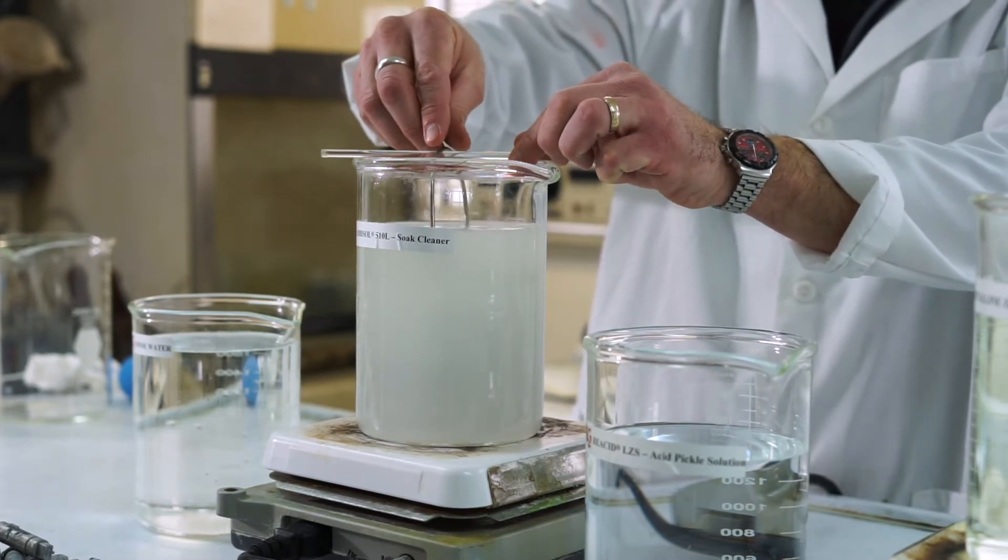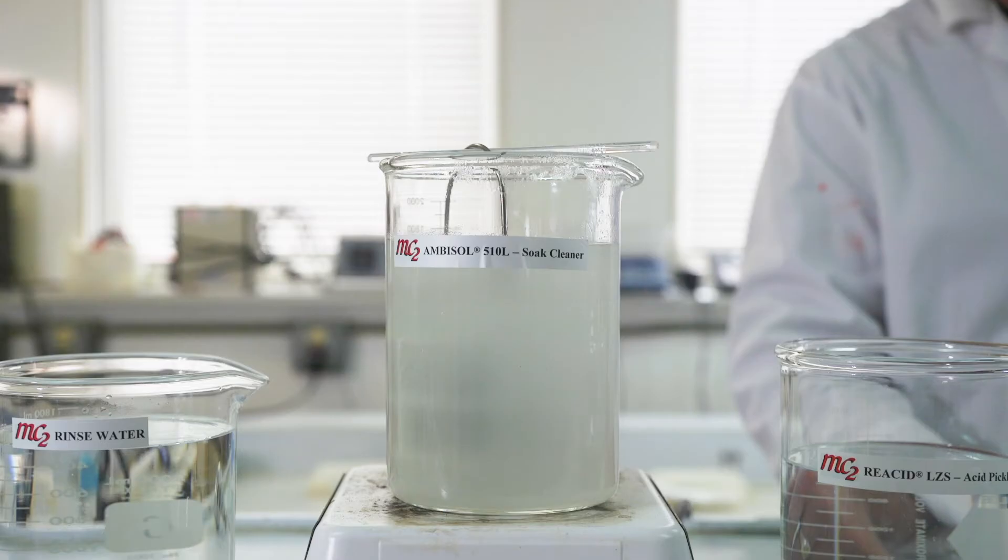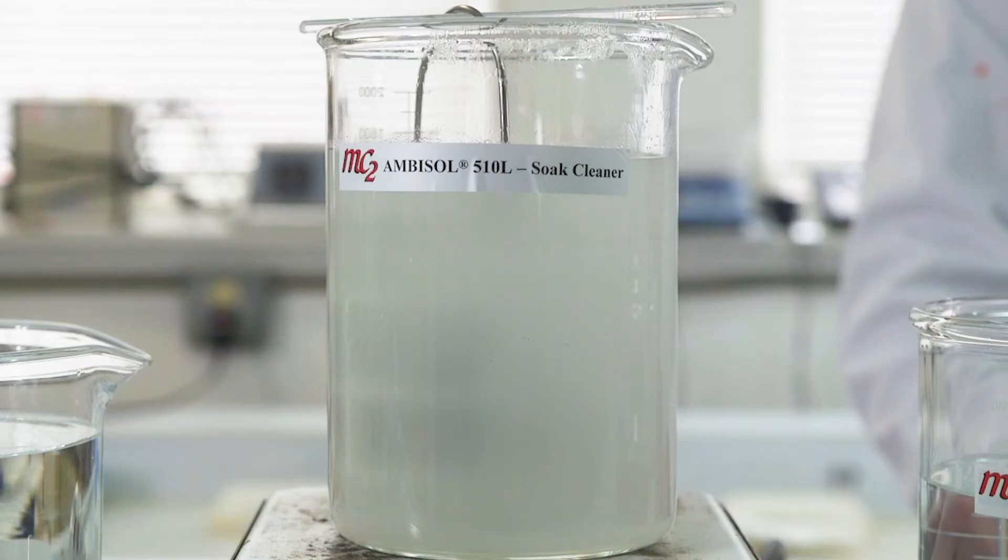This cleaner is made up at 10% by volume, has an operating temperature of 140 degrees Fahrenheit, and has a typical immersion time of 5 minutes.